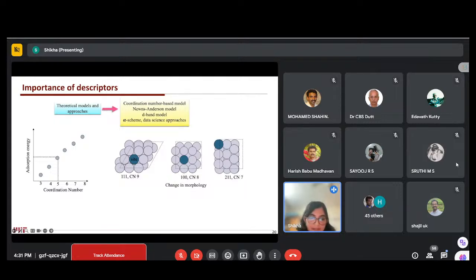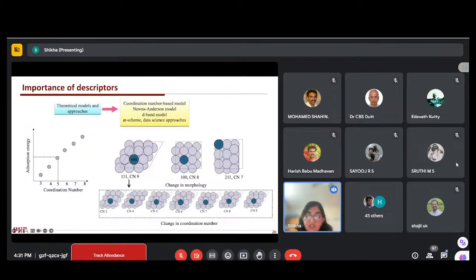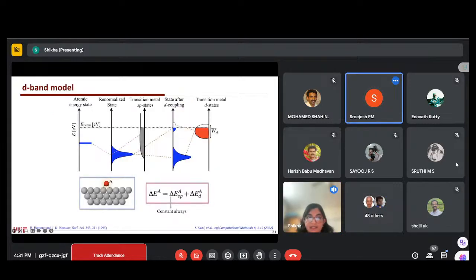So that way the given property we can correlate with the adsorption energy. We know that adsorption energy linearly correlates with the coordination number for a monometallic system. So if we decrease the coordination number, we increase the adsorption energy. For a lower coordination number, the adsorbate will bind more strongly to the surface. And we can also knock out the metal atom around the site, and that way we can reduce the coordination number. Another property is the d-band center, and there is the d-band model, which is very famous in catalysis, by which we predict which particular material or site would be reactive for the reactant. So what is the d-band model?